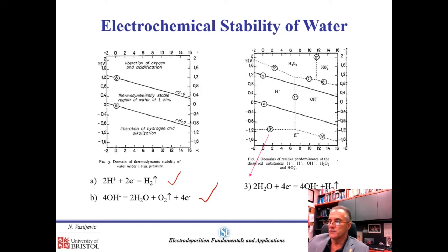One thing that you should keep in mind is that if you really drive your overpotential to negative, and the electrode surface exceeds this dotted line here, which is about minus 1.2 volts, then you enter the region where you start direct reduction of the water. So this is not the hydrogen evolution reaction as defined here, although there is an abundant hydrogen presence when you start doing direct reduction of the water. But it's a different reaction because here your reactant is the water molecule.